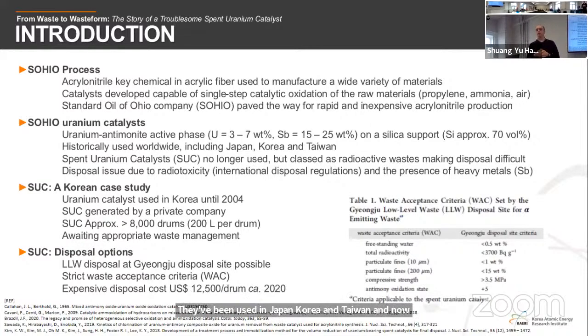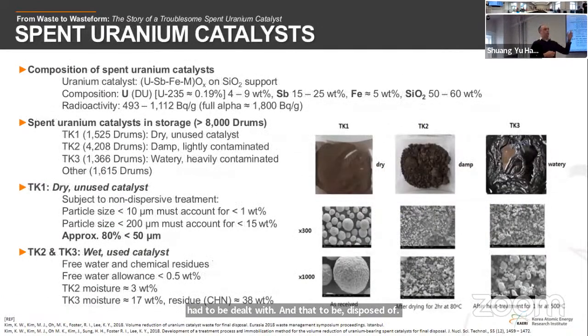So as I mentioned, there was a chemical company in Korea using the SOHIO process for taking raw organic materials and converting them into polymer chains, acrylic fibers for further fabrication. And this used a catalyst that contained uranium and antimony on a silica support. It had been used in Japan, Korea, and Taiwan, and by the end of use in 2004, there were about 8,000 drums in storage. This was just left in storage on the industry site, and it had to be dealt with and disposed of. The problem was that the waste was looking a bit like this.